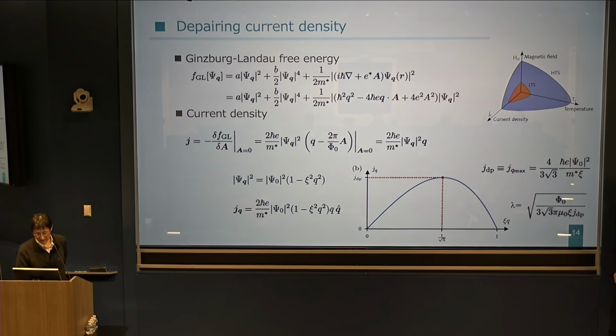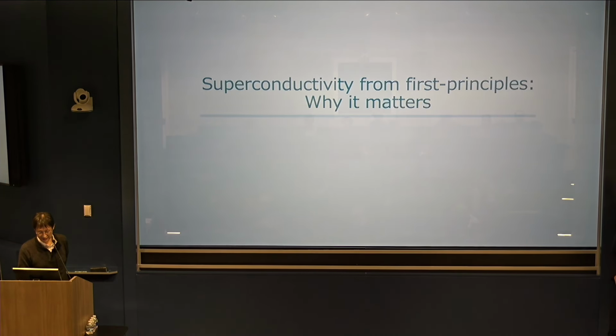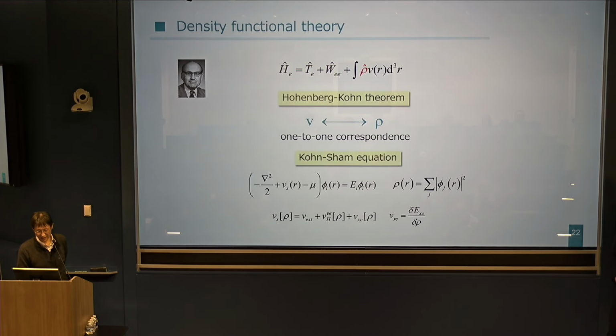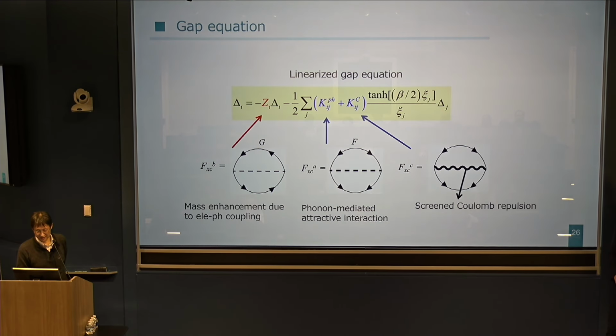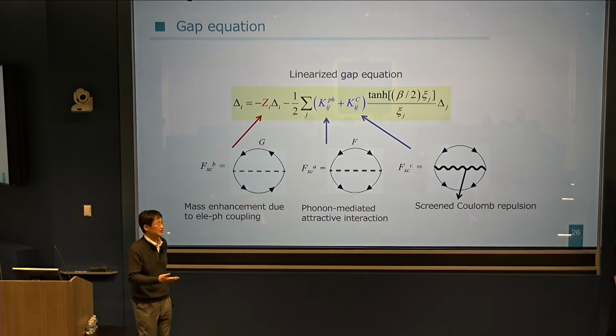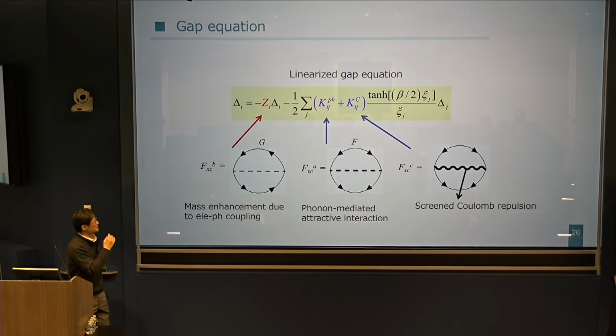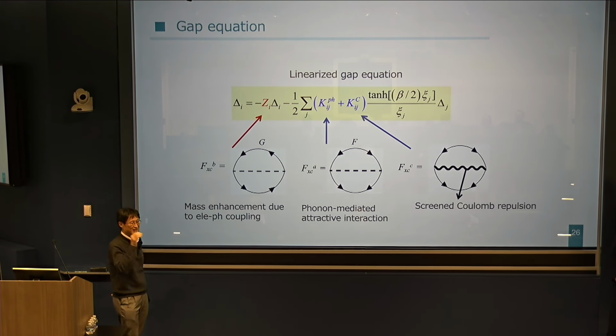Regarding the second question, in the framework of SCDFT, we do not introduce the pseudo-Coulomb potential. Because these equations, these quantities, are all static, maybe you may think that the so-called retardation effect cannot be described in these equations. But there is a quantum orbital dependence. The quantum state dependence of Kph and Kc is very different. So without introducing mu star, we can describe the retardation effect effectively.